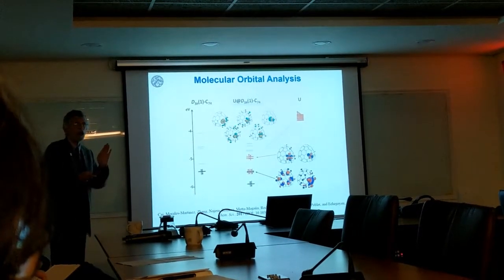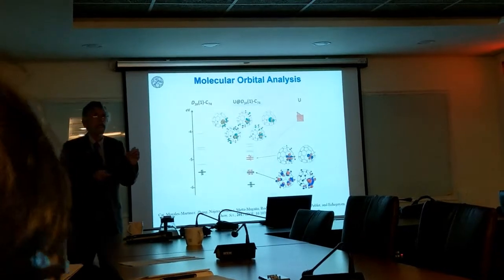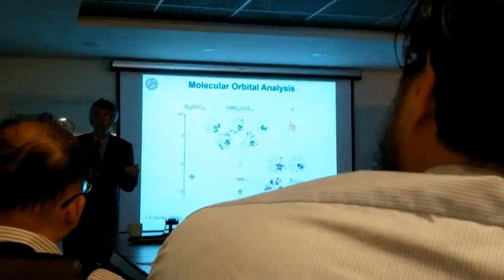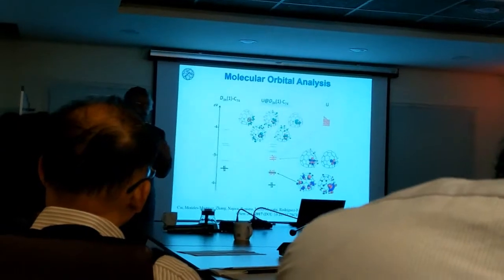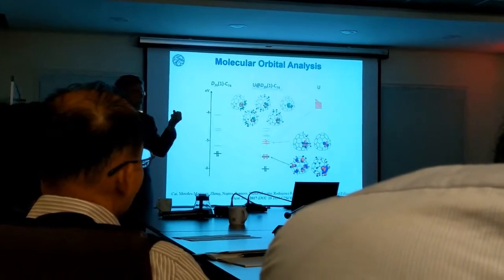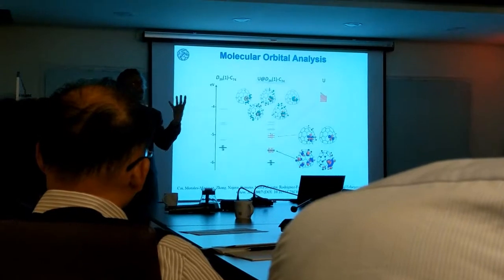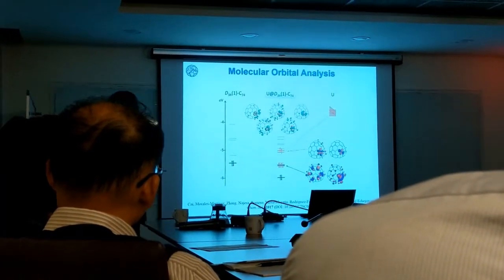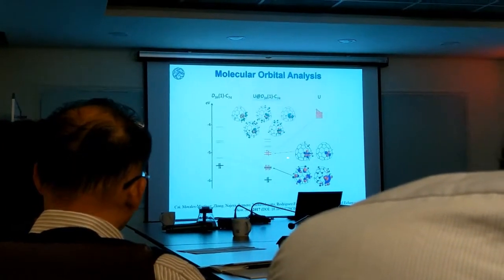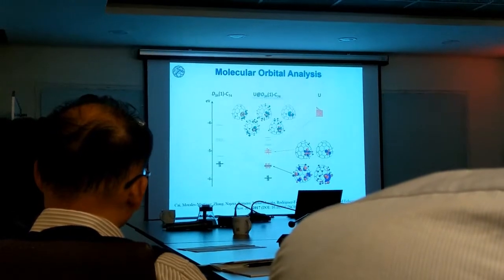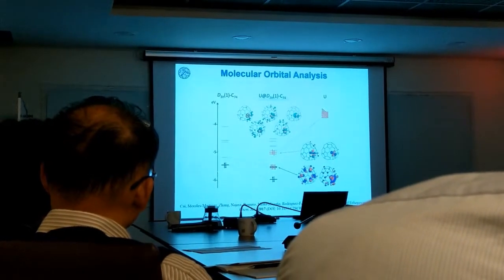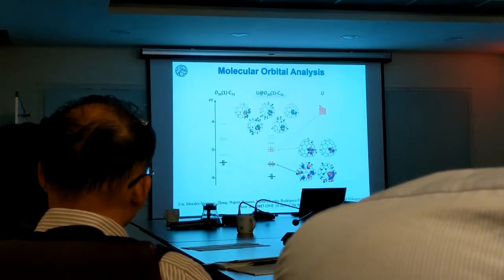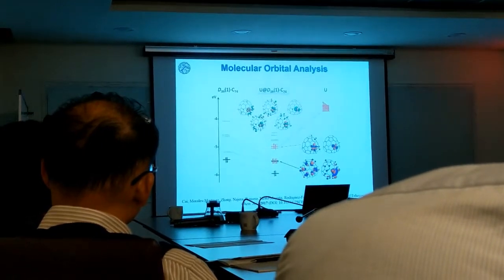Okay, that's pretty much always the case when you make endohedral metallofullerenes and cluster fullerenes. You always have a very pronounced charge transfer from the cluster or the atom to the cage. Okay, so formally this is a 4-electron transfer, so you end up with 2 electrons that are mainly localized, as you can see, in the uranium. These 4 are fairly delocalized over the cage.